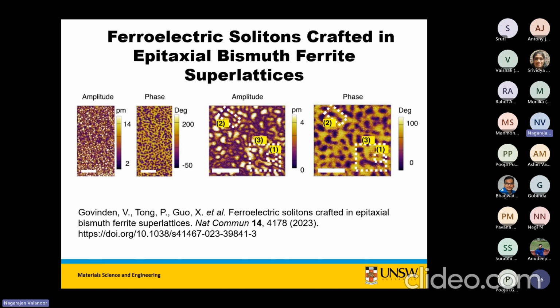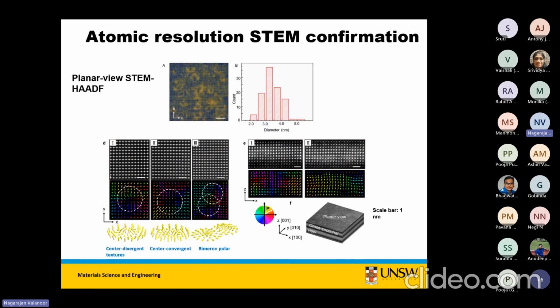So obviously, just doing PFM is never enough. Nowadays, even if you want to say something very mundane, like I'm growing my films epitaxially, the referee will say, I want an aberration corrected STEM image. So here's an aberration corrected STEM image that shows displacement mapping of the individual structures. And if you look at the paper, we had a lot of difficulties with one particular referee who said, oh, you're cherry picking data and showing only those regions which are showing these structures.